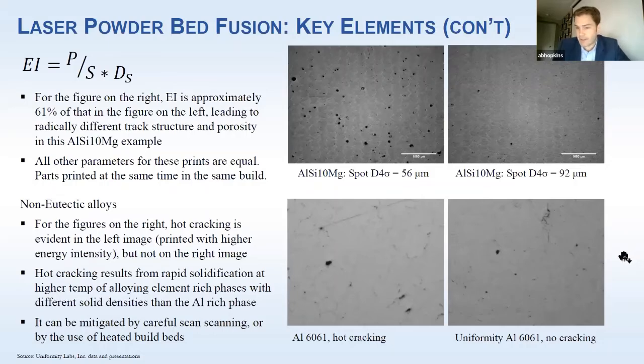So changing the alloy chemistry is also a really high potential area. And what you need to do is change it in such a way that you avoid these types of issues, as well as changing the scan parameters and changing the powder. There are lots of variables you can play with. And the result is you can eliminate pretty serious metallurgical problems if you're careful.